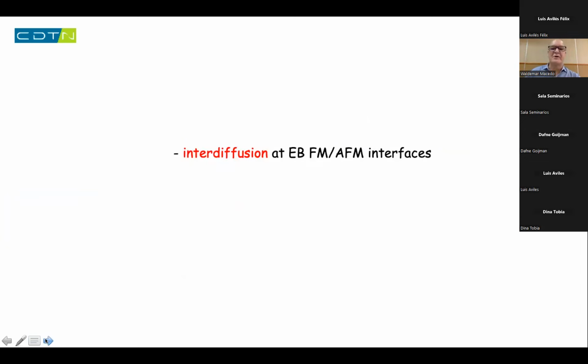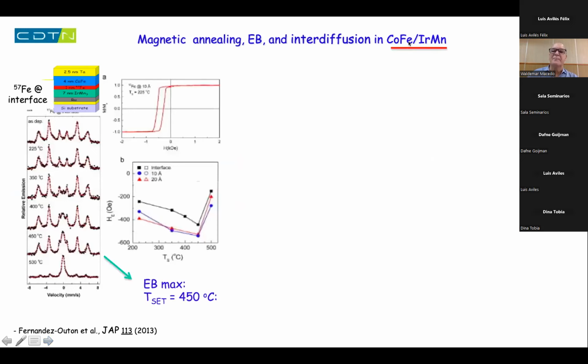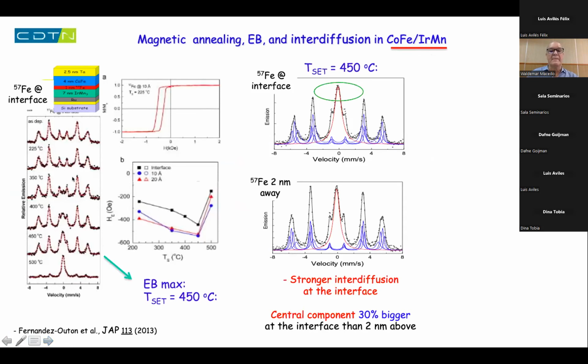Another thing that we have been studying that is important in this system was interdiffusion at this interface. For a device, for example, it can be very important to know how the interface behaves. We have been testing the cobalt iron iridium manganese interface, which is a model system for industrial application of exchange bias. For this system, when you do the magnetic annealing to improve the exchange bias, up to 450 degrees you have a small central peak, which is a sign of interdiffusion in the system. At 500 degrees you have a strong interdiffusion. And although you still have a very significant exchange bias, the diffusion is really high above 450 degrees centigrade, and the exchange bias is maximum at this temperature.